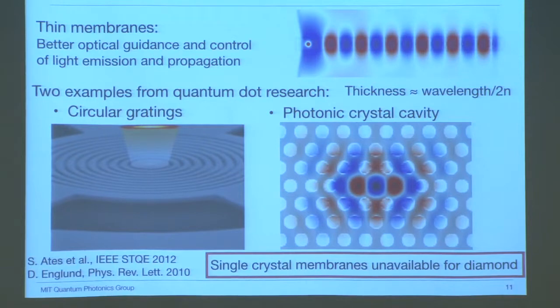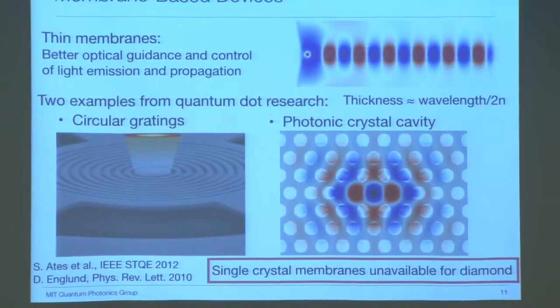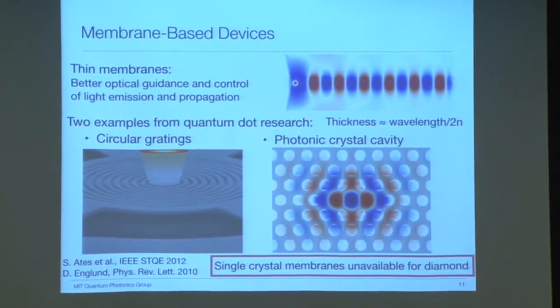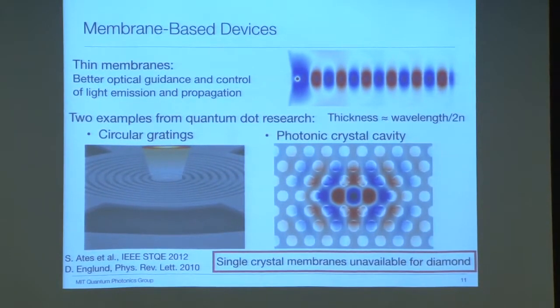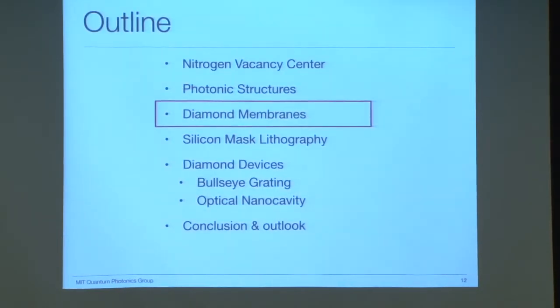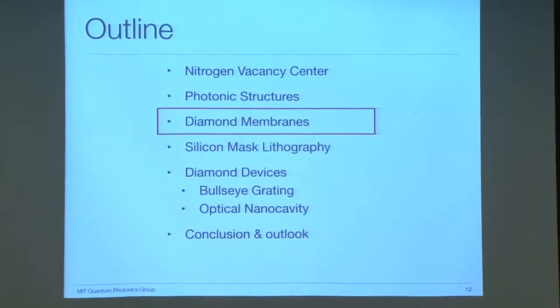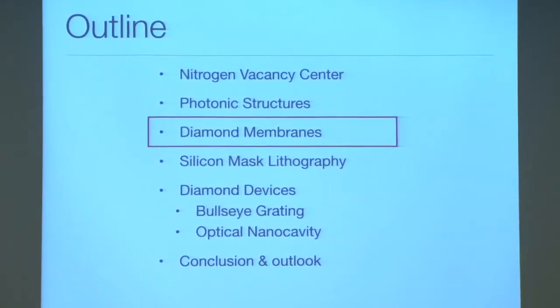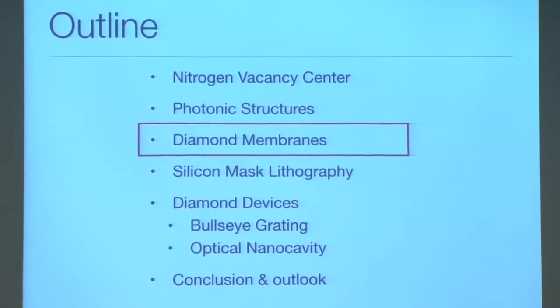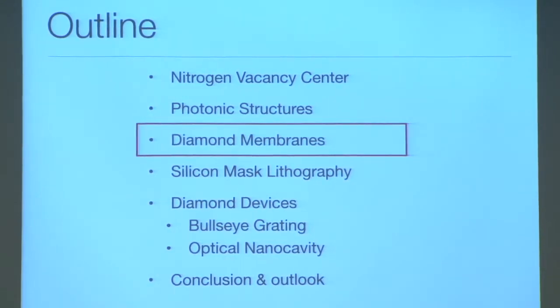Unfortunately, single crystal diamond membranes are not commercially available, and before we are able to fabricate these devices into the diamond, we need to first figure out ways to produce diamond membranes ourselves. Diamond could be grown by chemical vapor deposition, but 200 nanometer high quality single crystal diamond membranes are not possible to grow so far. And I will now introduce 3 different approaches that we developed and applied for diamond membrane